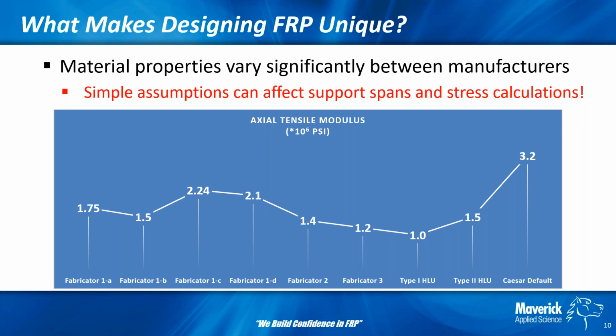Basically, what the viewers need to know is there is some of the gap filled with NM2 and NM3, where there are stock properties in NM3 for FRP type 1, type 2, and type 3 laminates. So you don't have to do all of this guesswork. You can just use a stock value, but it will be conservative. And that also goes for allowable stresses too. People would be happy to note that there are allowable stresses published in NM3.